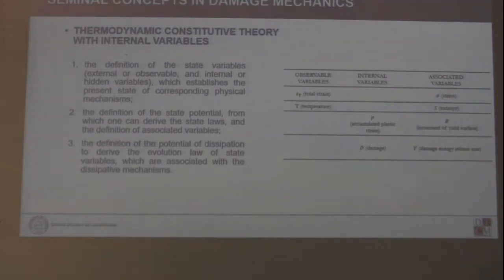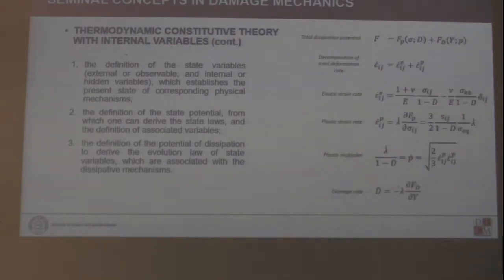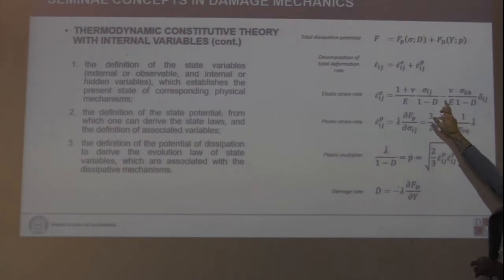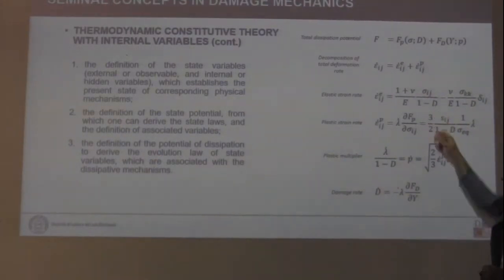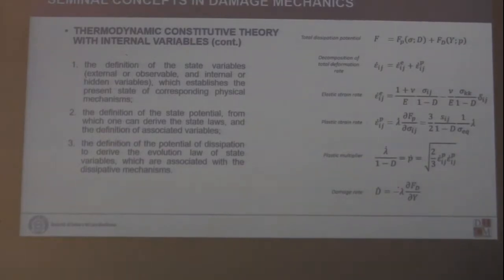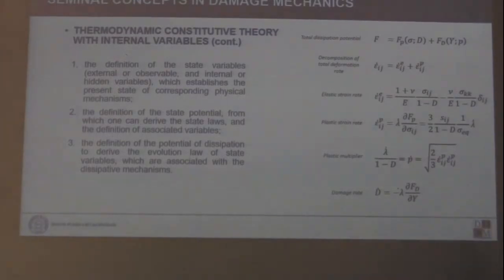a consistent thermodynamic model. In continuum damage mechanics, by the use of the effective stress, we can simply assume that the constitutive equations for a damaged material are the same set of equations for a virgin material that come from continuum mechanics, just simply replacing the stress with the effective stress. So the system holds, but we have to introduce now an additional state variable, which is the damage, for which we need a damage evolution law. And the damage evolution law can be derived providing the damage dissipation potential.